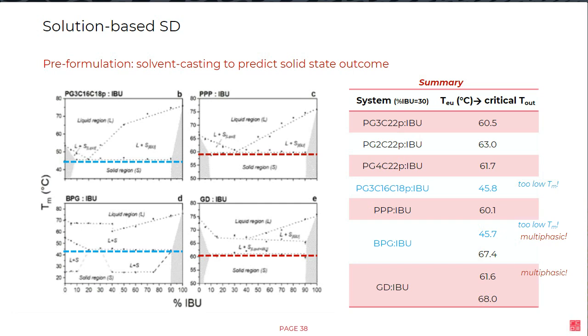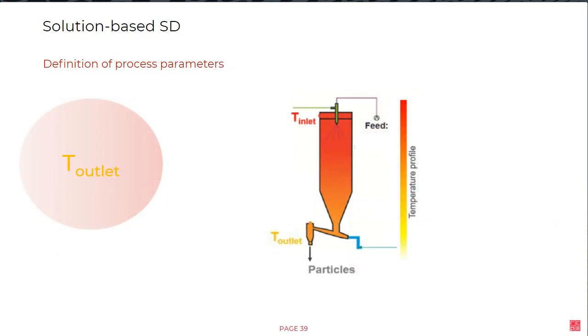The other lipids are either showing multiphasic systems like the one you can see in BPG ibuprofen, for which many liquid and solid regions are mixed, and this will provide a risk of phase separation during spray drying. The rest of the lipids, as you can see, have only one melting temperature, the eutectic temperature of around 60, 63 degrees more or less, which might still be processable by spray drying. So we use these eutectic temperatures to provide a rational boundary for a critical outlet temperature. Based on this, we can go to the next part, which is to define the process parameters.